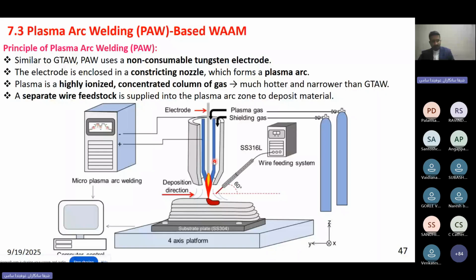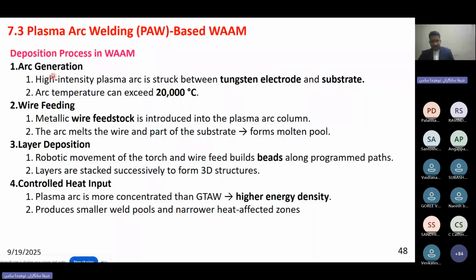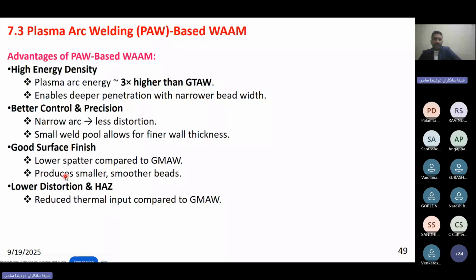So arc generation, wire feeding, layer deposition, and controlled heat are the steps involved in the plasma arc based WAM technique. Here the energy density is high: once the plasma is generated, the temperature will be around 10,000 to 20,000 degrees centigrade. So the energy density will be very high, almost 3 times higher than the gas tungsten arc weld based one. Moreover, we get a narrow arc and narrow droplet, which is good for the product. So better control and precision, good surface finishing, and lower distortion and heat affected zone when compared to the previous technique. Okay, this is the plasma arc welding based technique.